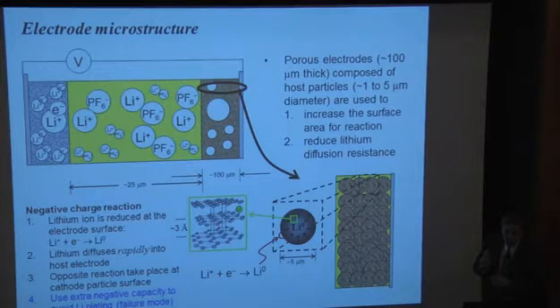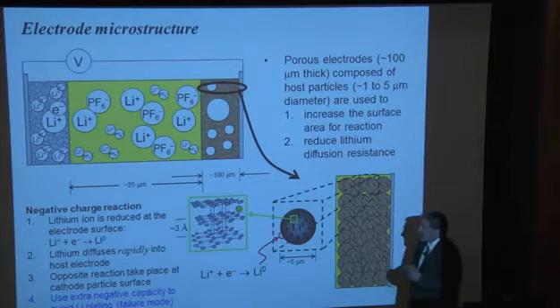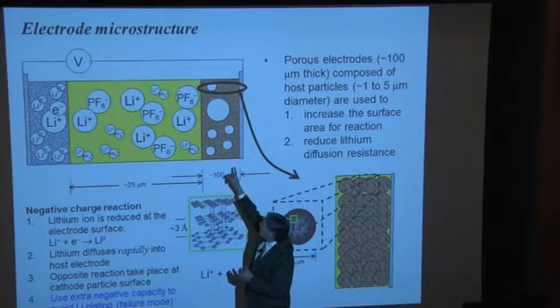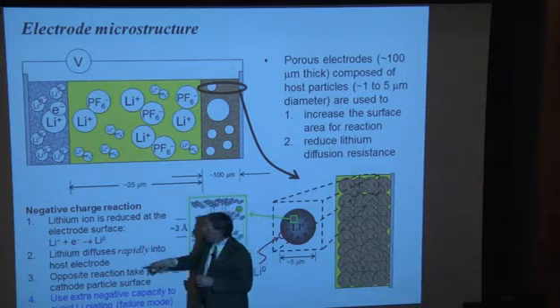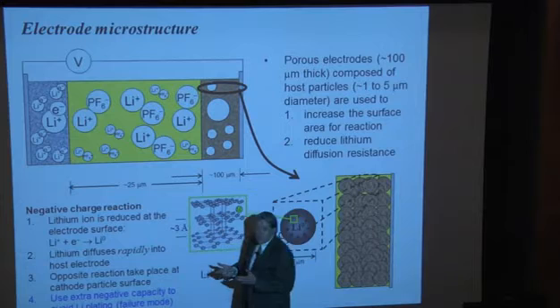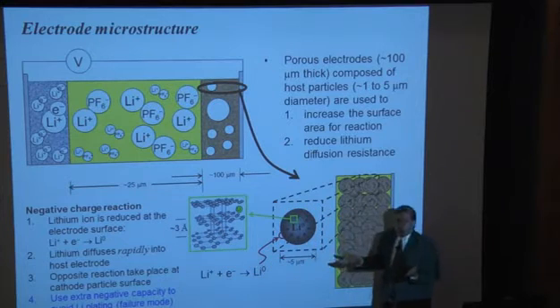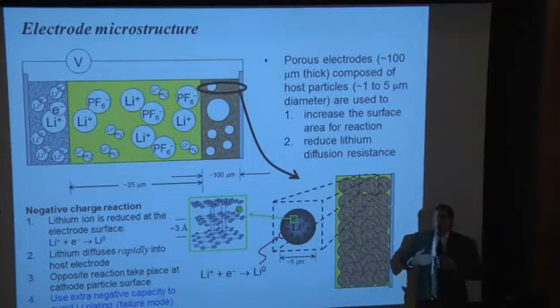Now, when you first construct a lithium-ion battery, you use an excess of negative electrode, and that's because once you've filled the carbon electrode, the next reaction to occur when you keep on reducing lithium to fill up the electrode would be lithium plating. Lithium is extremely reactive. It's 3 volts negative to a hydrogen electrode. It's an extremely reducing atmosphere.